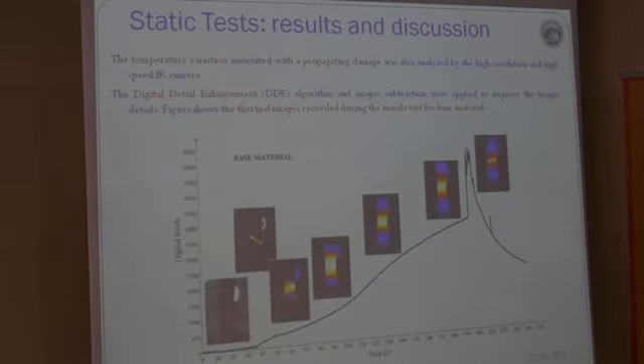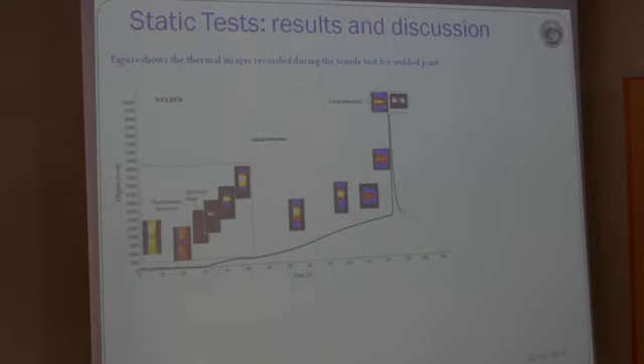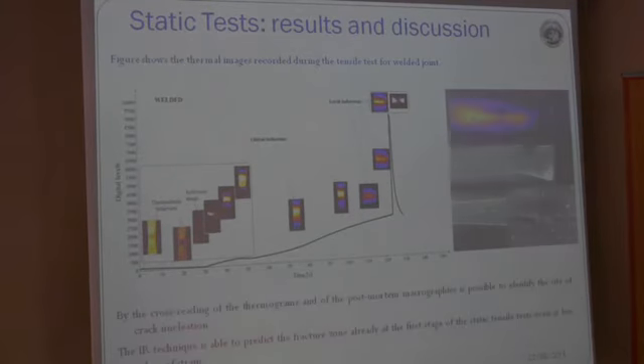This slide shows the temporal evolution during the static test for the base material. This is a thermal image, and this is for the welded joints. We can see that the IR technique is able to predict the fracture zone, and in the right figure with the macro photo, you can see this.